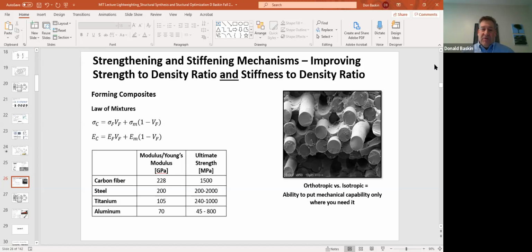I don't know how much you know about composites, but there aren't just carbon fiber with epoxy matrix, or fiberglass with polymer matrix. There also are what's called metal matrix composites, where you can put, say, a ceramic fiber in aluminum. The 3M Corporation makes some very strong aluminum composites by taking aluminum oxide fiber called Nextel, infiltrating it with molten aluminum and then cooling the aluminum. That forms a composite of aluminum and aluminum oxide fibers. Very, very strong, very, very stiff. I actually have a panel in my backpack here that is made out of this material, which I'd love to show you because it's incredibly stiff compared to normal aluminum. If we were in class, I would pass it around the room, but unfortunately I can't do that.